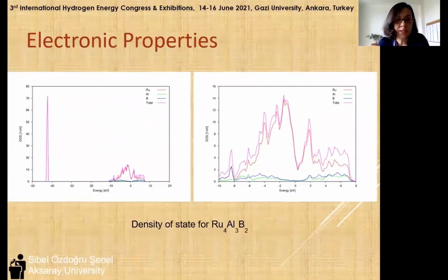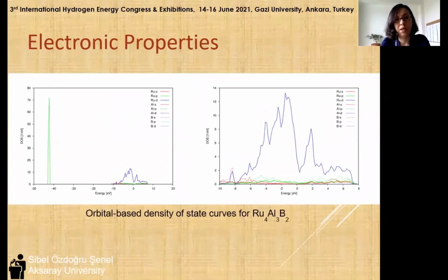Density of states curves were also plotted. The low density of states at the Fermi energy level indicates that the material is stable. It can be said that the conductivity is predominantly provided by ruthenium elements. This graph shows which orbitals contribute to the density of states. Ruthenium-D orbitals are dominant contributors in both the valence and conduction bands.